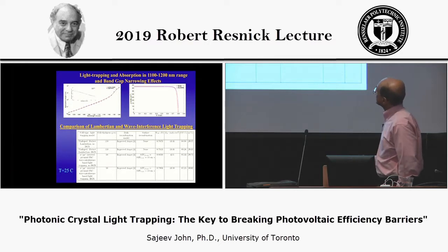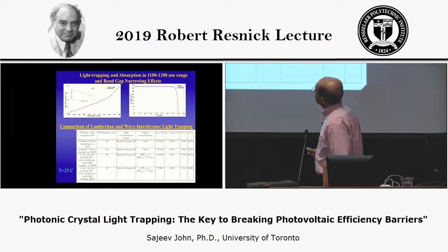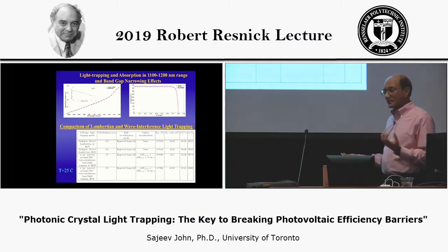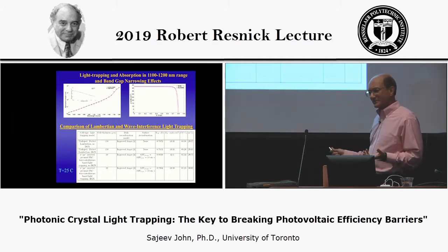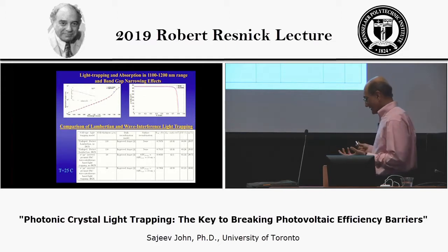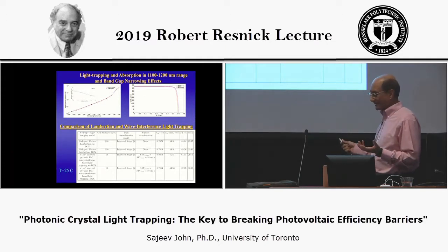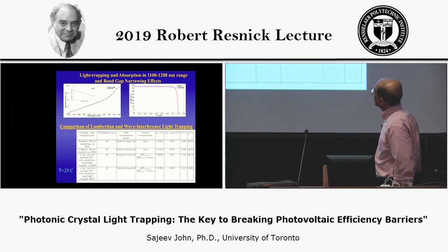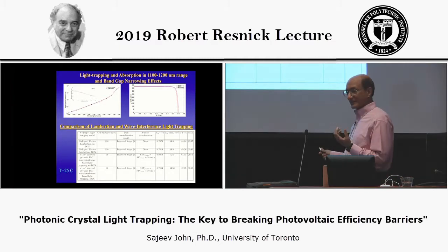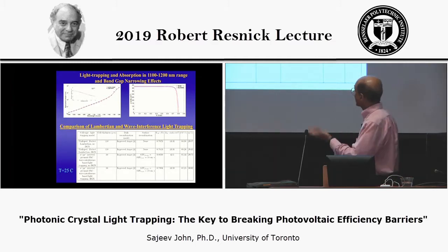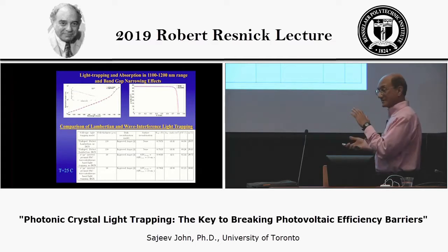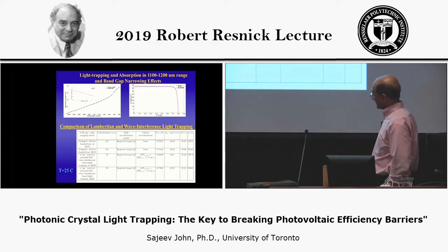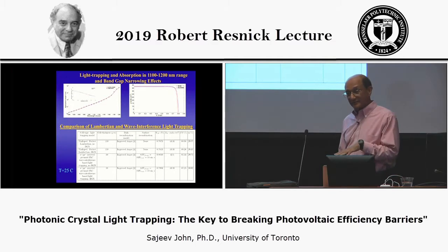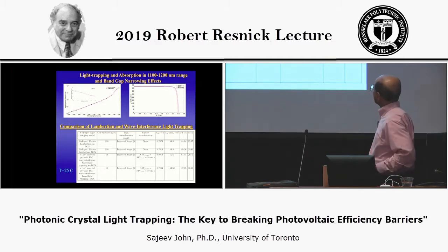Now we can also consider the region between 1100 and 1200 nanometers. Usually in ordinary solar cells that doesn't really do you much good because it just doesn't absorb much light at all. There's not enough light trapping, and what happens is that there's an effect called band gap narrowing. As a lot of carriers are generated, it actually lowers the band gap of silicon a little bit, and that actually reduces the voltage generated without increasing the photocurrent density.